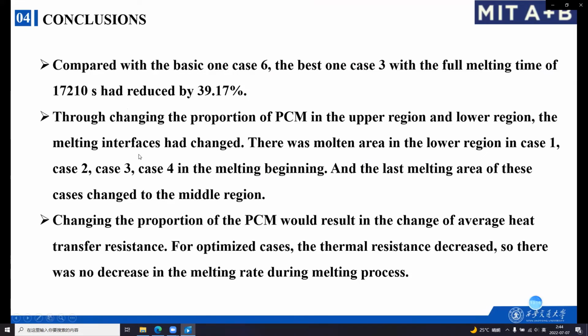The melting interfaces had changed. There was molten area in the lower region in case 1, case 2, case 3, case 4 in the melting beginning, and at 8000 seconds, the liquid PCM near the tube in case 1, case 2, case 3, case 4 was larger than other cases, which was conducive for natural convection. And the last melting area of these cases changed from the lower region to the middle region.